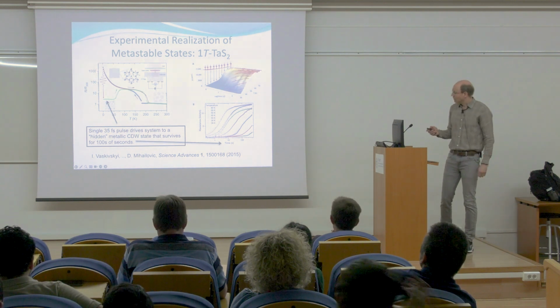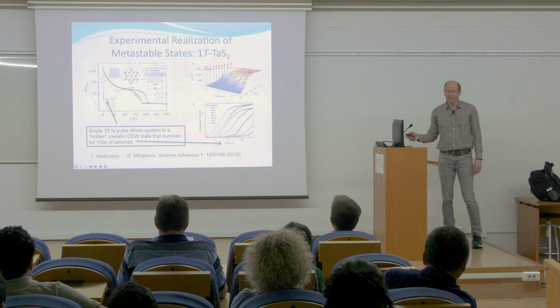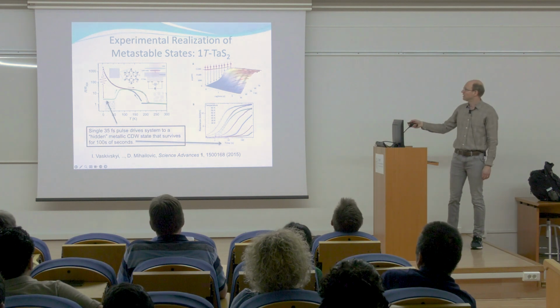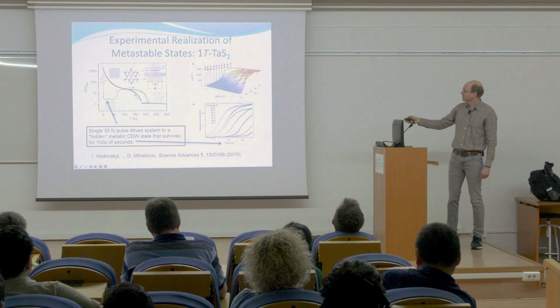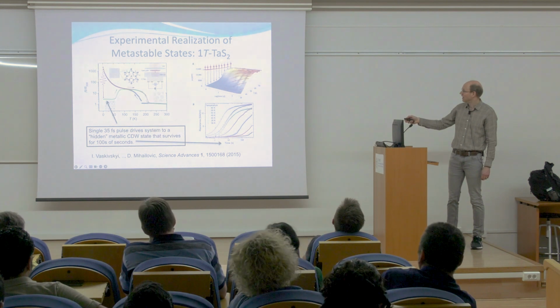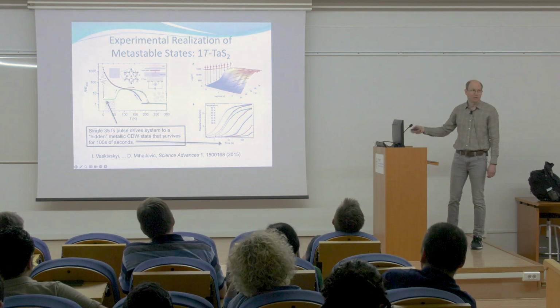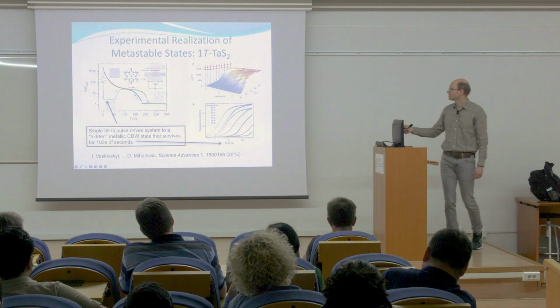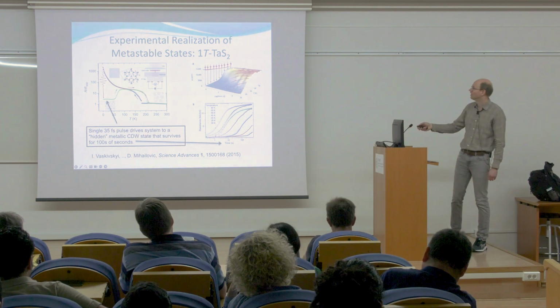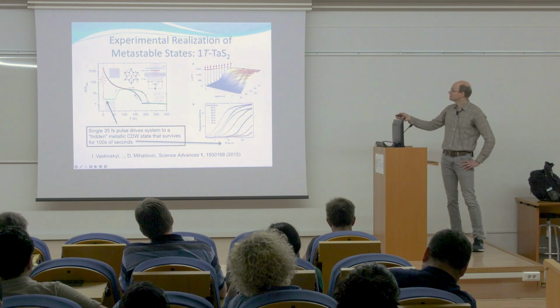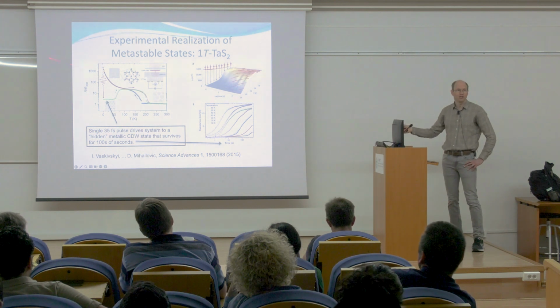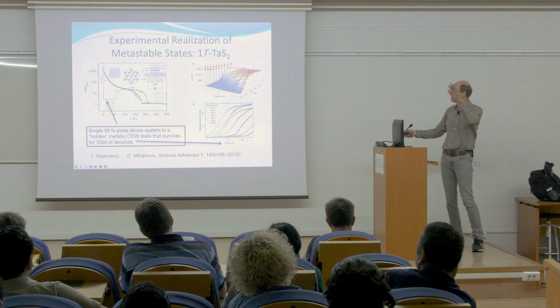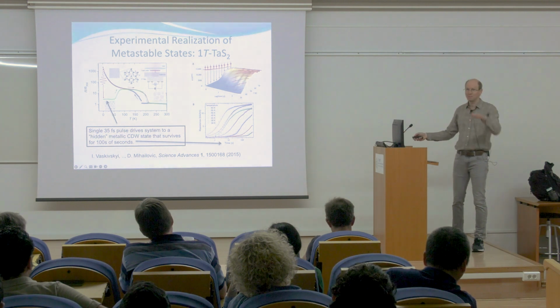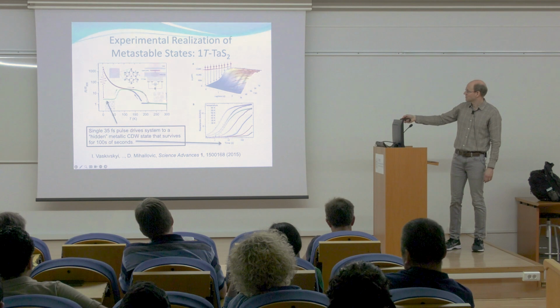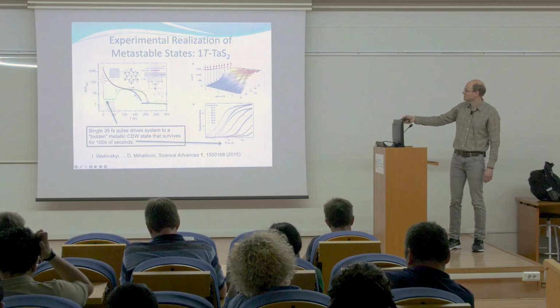Okay, so let me give some experimental examples now of systems that have been irradiated with light. This particular material here, tantalum disulfide, and the 1T refers to a particular crystal structure in the system, which is not important for us. The important thing is that this material has a charge density wave order, so there's some modulation of the electronic charge in space. That's shown here and here in image pictures.